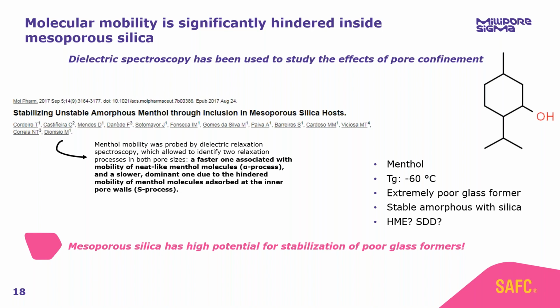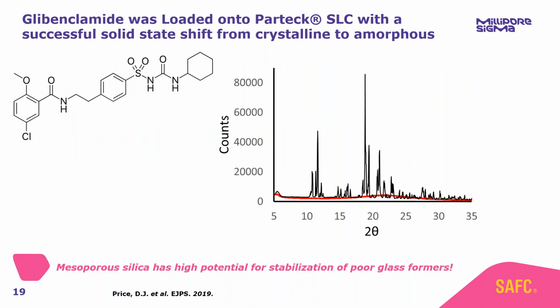Now, of course, no one is trying to develop an amorphous menthol formulation for the market. And so we wanted to repeat this study with a more pharmaceutically relevant compound. In this case, we turned to glibenclamide, and we successfully loaded glibenclamide onto mesoporous silica in the amorphous form. You can see the crystalline structure of glibenclamide there in black, the characteristic Bragg peaks on the XRPD. And in red, we have glibenclamide loaded silica. We no longer have those Bragg peaks. We have an amorphous halo because our molecule is successfully stabilized.